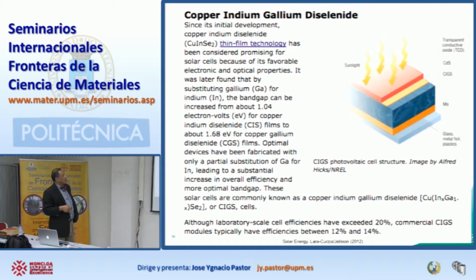And then you have your PN junction with cadmium sulfide and your CIGS in the bottom. These are becoming more and more effective. Your band gap, again, is around 1.04, so that gives you a slightly different part of the spectrum compared to silicon. And efficiencies between 12 and 14%. At the laboratory, they can do better, but in terms of mass production, that's what you get.